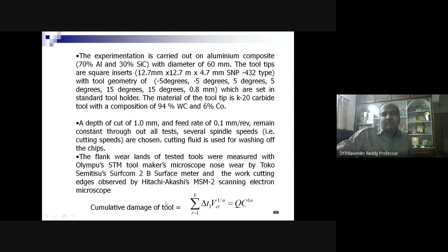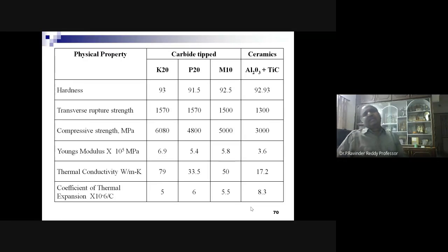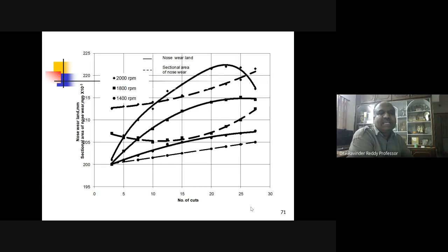The theoretical equation gives the cumulative damage of the tool as the summation from i equal to 1 to k, because we are going to consider the through contact, delta t_i V_cr to the power 1 by n, in other words, Q C to the power 1 by n. These are the material properties of the tools we have used: carbide tipped K20, P20, M10, then ceramics, aluminum oxide with titanium carbide. These properties are required, and you can plot nose wear and sectional area of nose wear at different cutting speeds. The cutting speeds selected are 1400 RPM, 1800 RPM, and 2000 RPM.